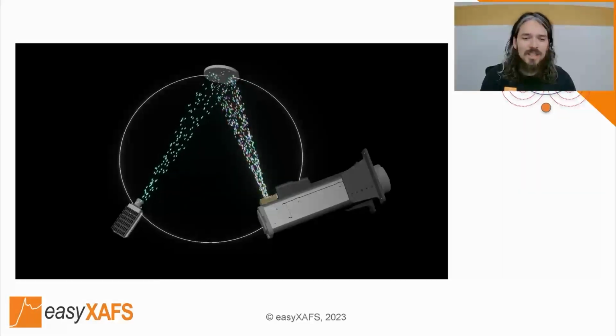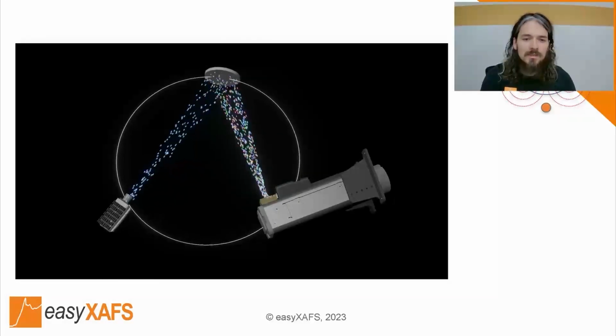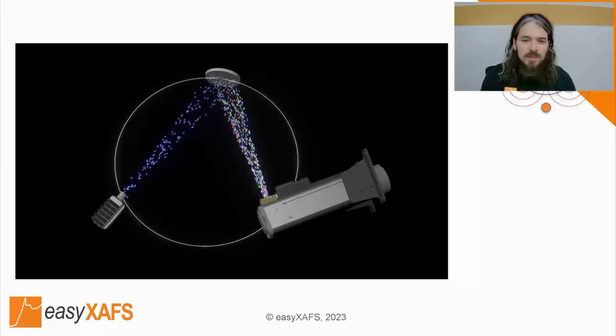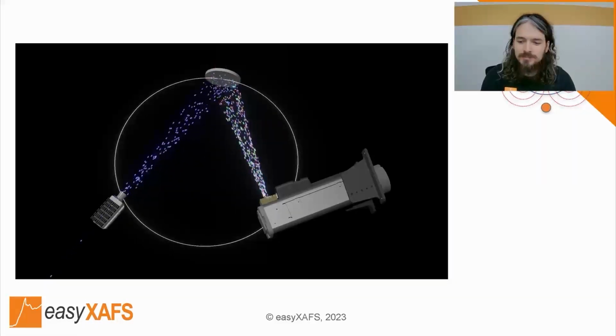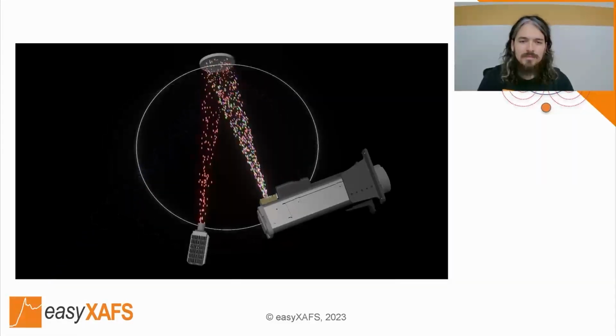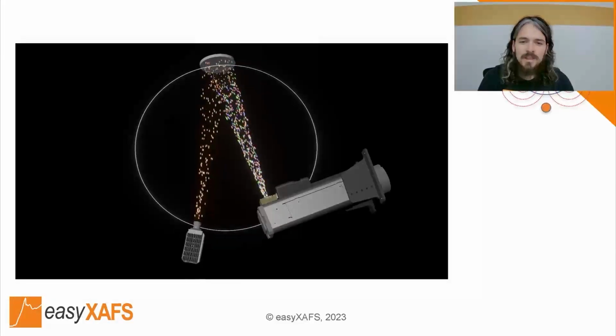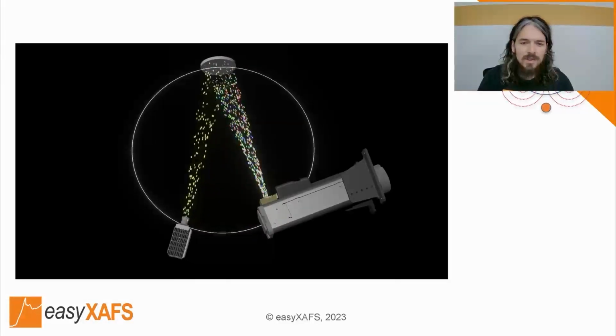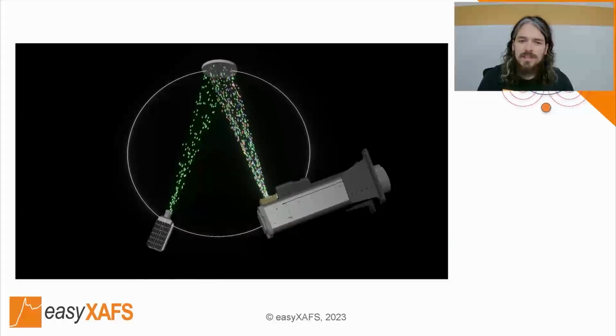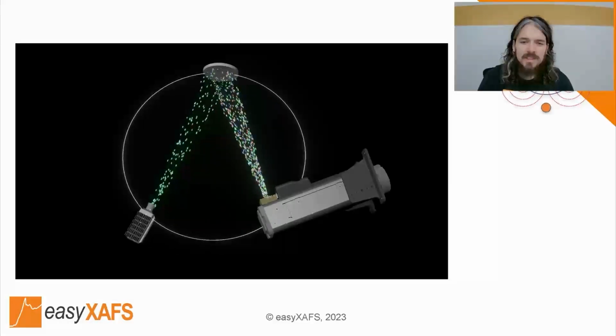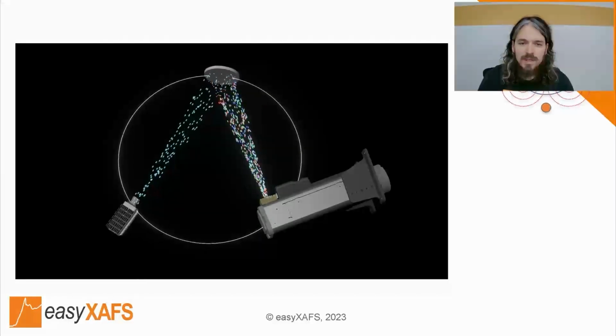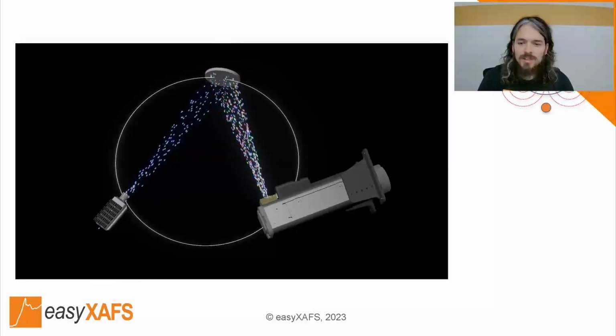So this is how we achieve a monochromatic, tunable X-ray beam that we can sweep over a range of energies to build up our XAFS measurements. Letting that animation play through one more time, we can see how the components move relative to one another. There are 4 motors that control the positions of the components to achieve the desired changes in Bragg angle to step through the energies of the measurement.